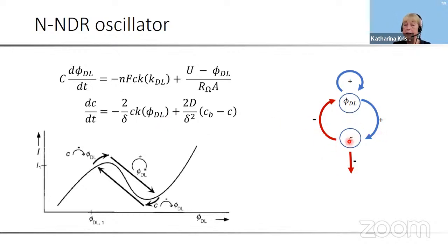Let's see why C, in fact, on the one hand, is activated by phi dl, which means that if phi dl increases, I go to a larger value, also C should increase. And why C, on the other hand, a large C leads to a decrease of phi dl. So let's say this is some base current potential characteristic, and we perturb the electrode potential a little bit. We have already seen this leads to a lower current, and a lower current means that this term becomes smaller. So the decrease of C becomes less than in the original steady state, which is unstable, and C increases. So this is this positive feedback.